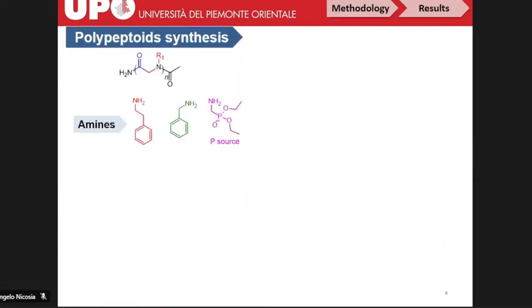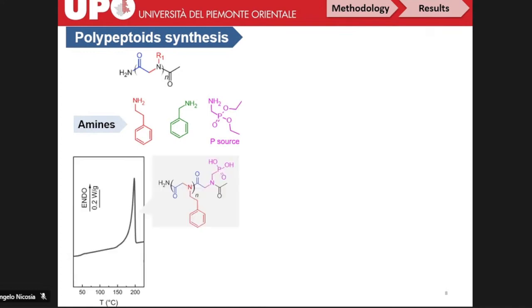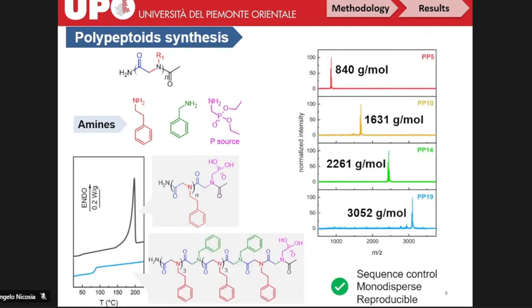So we use these amines, and at the beginning we tried to synthesize a homopolymer, but we found that it was crystalline, and then to resolve it, we inserted these functionalities to avoid the crystallinity. And using this strategy, we were able to synthesize 4 polypeptoids with diverse molecular weights. And as you can see from the MALDI-TOF results, they were monodisperse, and this technique allows us also to have a reproducible strategy to produce the polymers.